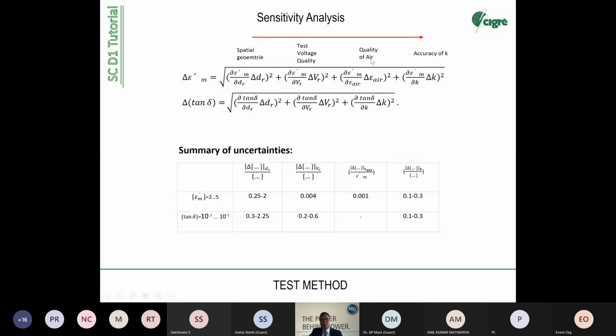Quality of air is a minor influence. It's mainly the moisture, but accuracy of the correction factor of the arrangement is a contributor. So these are both the sensitivity analysis for the quality of permittivity and the analysis for tangents delta. You see the main contributors here. So if you want to measure epsilon in a range of 2 to 5, where most of our applications are, or tangents delta in the range from 10^-3 to 10^-1, you can have quite high disturbances here.